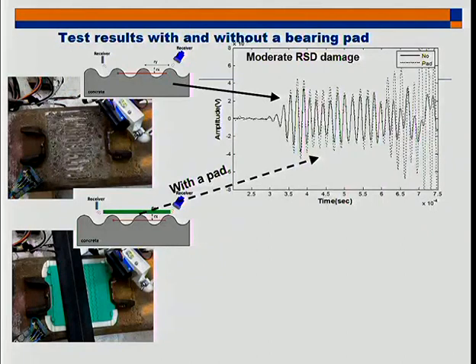Before we did this test, I thought that when the pad is in place, that is going to suck up all the energy, and we're not going to get any energy through. But what was very interesting is that not only did we not lose energy, we actually lost less energy because of the pad, which is a very surprising result. We still can't really explain why that is. It's a pretty consistent result. It may have to do something with an interface wave or the way that the wave gets bound in that interface. But the bottom line is we're not losing energy because of that pad.